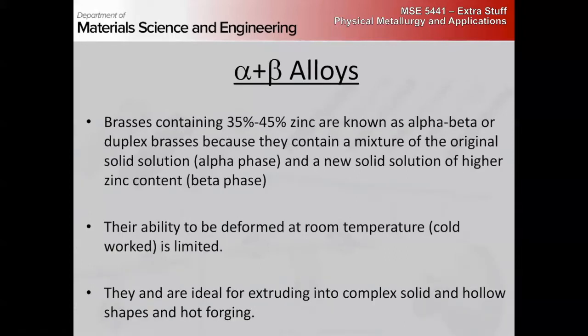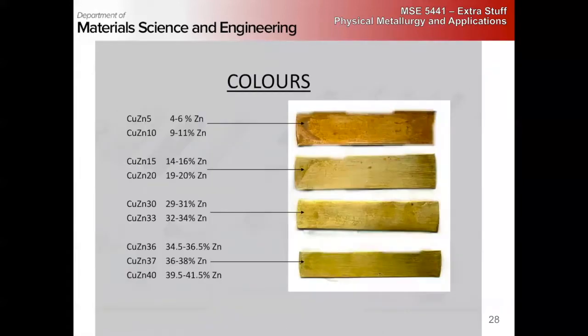The alpha brasses contain at least 63% copper, with real good ductility at room temperature, easily deformed by cold rolling and deep drawing. Those with higher copper content and lower zinc tend to be more golden in color and are used extensively for decorative metalwork. The alpha plus beta alloys tend to be higher in zinc, containing a mixture of FCC and BCC phases. They really cannot be cold worked, so they have to be typically hot extruded or hot forged into shape. They're used more for strength.